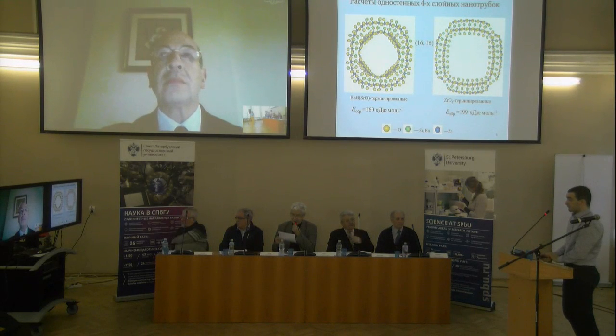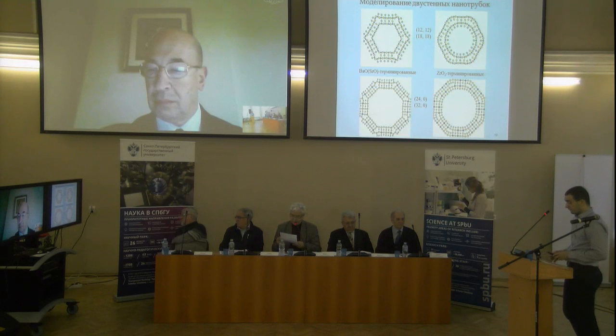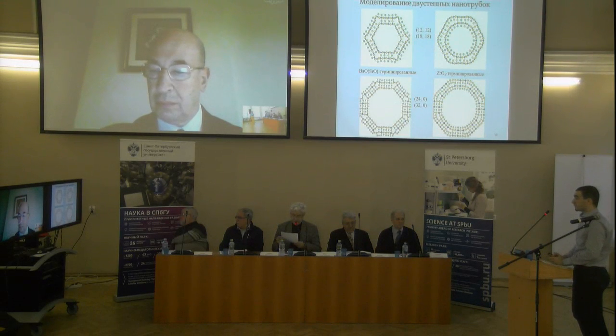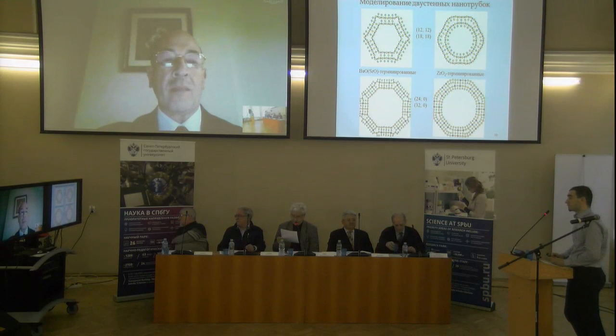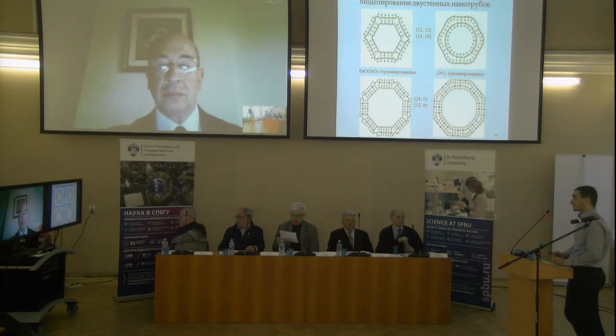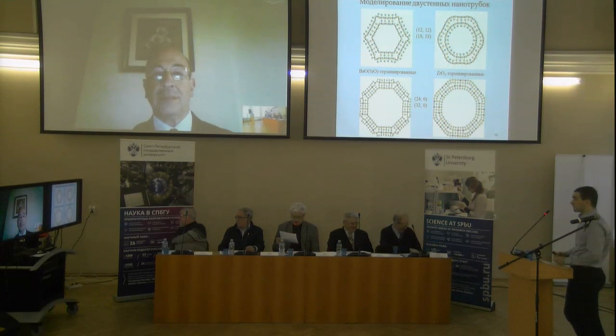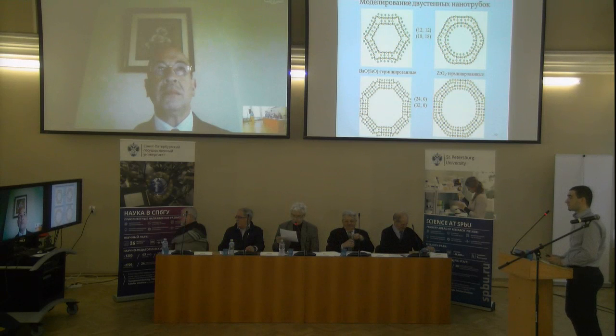SrZrO3 and BaZrO3 NT. The inner shell consists of one ZrO2 layer, and the outer shell consists of three ZrO2 layers. And that's figure 6a. The internal SWNT of zirconium oxide has hexagonal morphology of the zigzag type. Such a stratification is possible in connection with the close translational periods of NT from zirconates and NT from zirconium oxide.